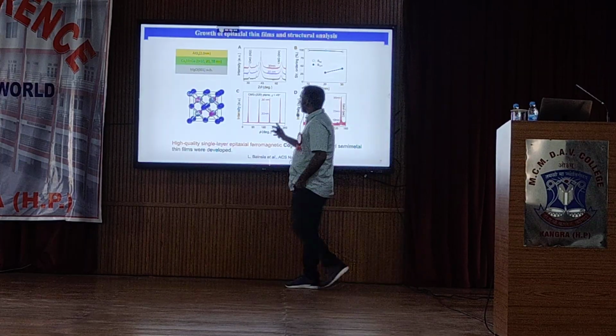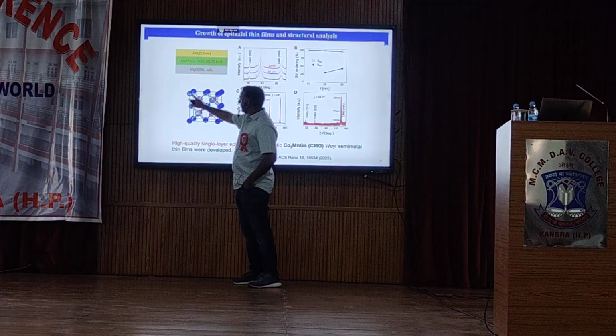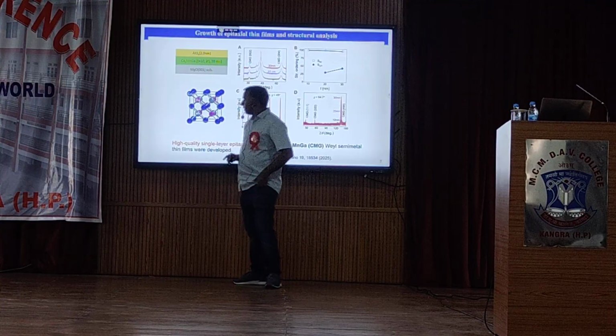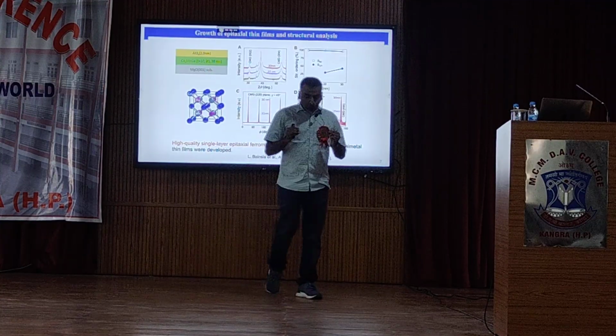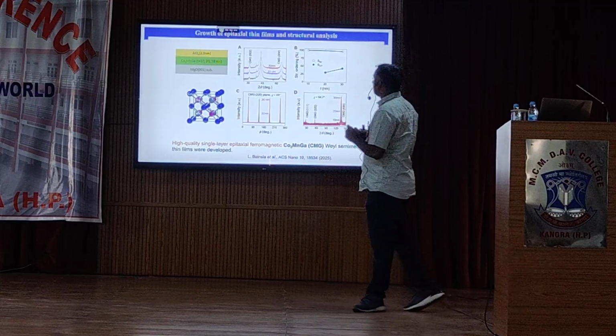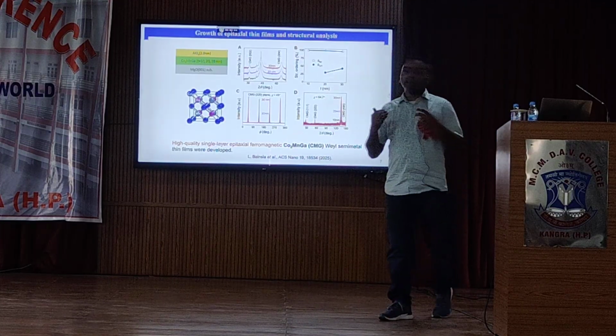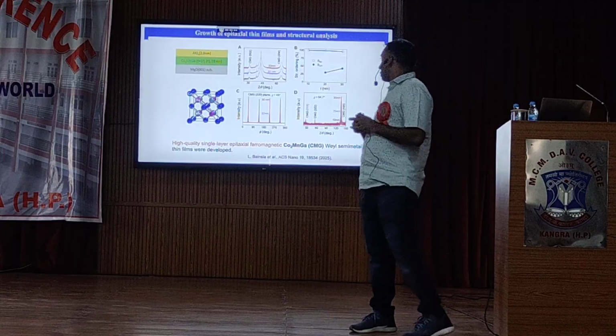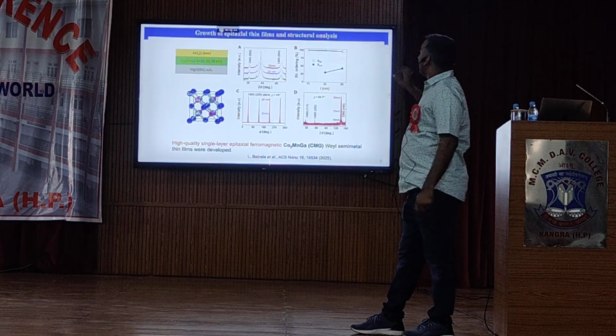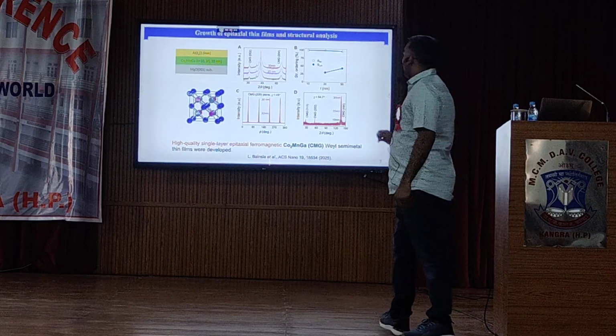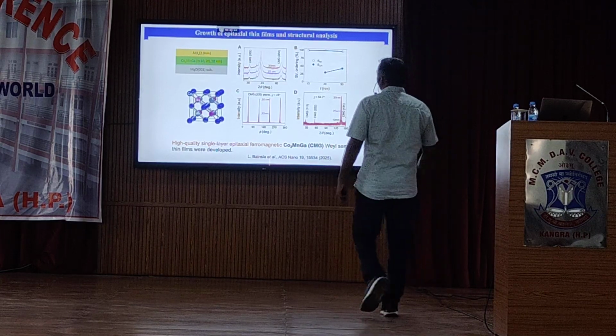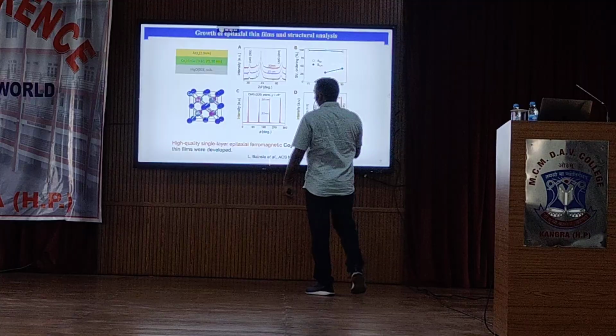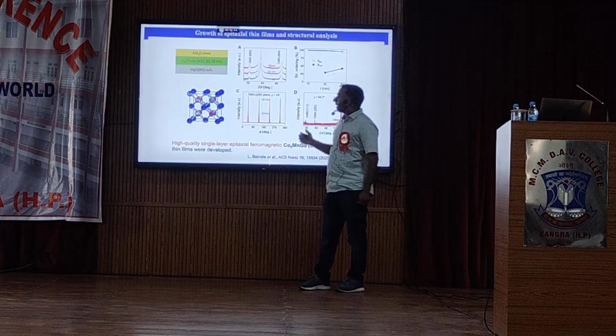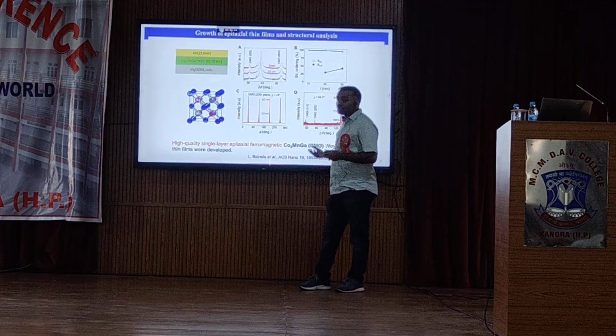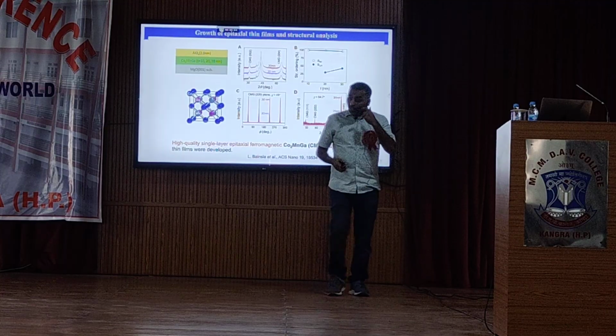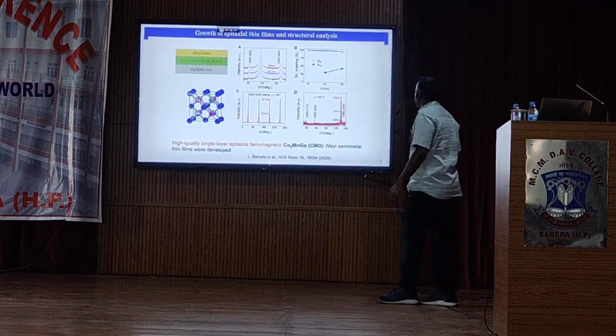We are then also interested in the material properties, like whether there is any antisite disorder when we grow thin films. We also expect that the atoms are not occupying their respective atomic sites. It is possible that cobalt can go to the gallium site and gallium can go to the cobalt site. It can also happen that manganese occupies the cobalt site and cobalt occupies the manganese site. So we also studied whether such antisite disorder is present in our thin films. That we confirm using XRD measurements.